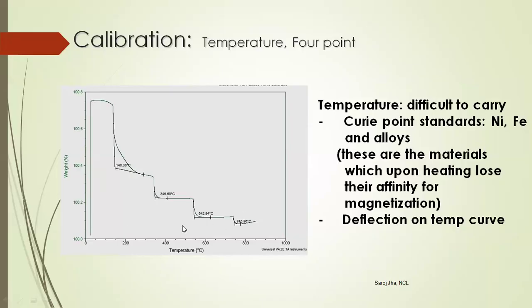So whenever you get a TGA or you have a doubt about the degradation temperatures of your material, if you have some temperatures in mind and your material is degrading before or after that, just take these Curie point standards and run a TGA, and you should see the standard sharp deflections at these 4 temperatures. This is the 4-point temperature calibration.